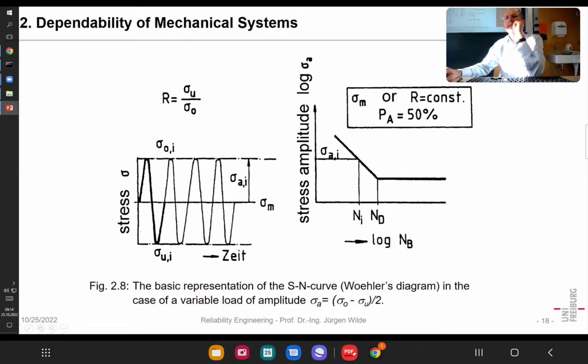And when you have reached that at a certain stress level, you often find that the specimen will live longer. Or when you are at a stress level below that, it also can live until infinity. That's not the case in every material, but in iron materials, steel, you could find it. And that's a basic representation of the so-called Basquin curve or the Wöhler curve, maybe a small difference.